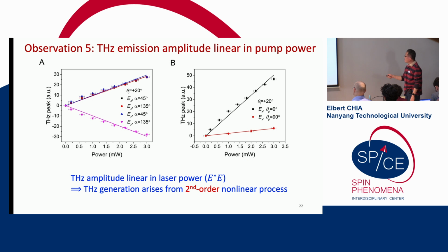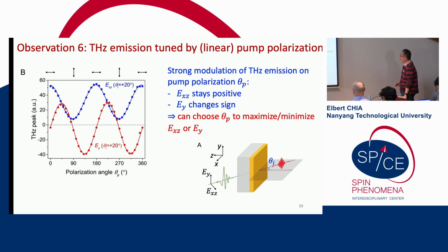We measured the Terahertz peak amplitude as a function of pump power. And so we found it's linear with pump power. So it is consistent with a second order nonlinear process. Next, we varied the pump polarization.